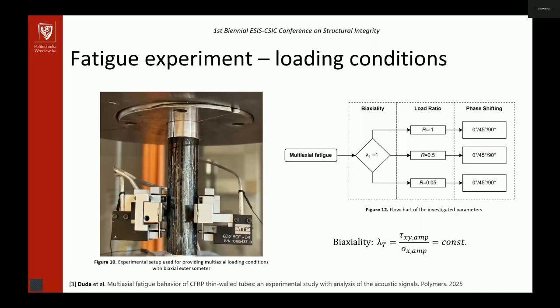All right, so the axial force was applied as well as torsional moment. You can see the flowchart of the investigated parameters. We have the biaxiality ratio. In this case, the biaxiality ratio is for the geometrical stresses, and it is equal to 1. So the geometrical normal stress is equal to the shear stress, for different load ratios, as well as for various phase shifts, 0, 45, and 90 degrees.